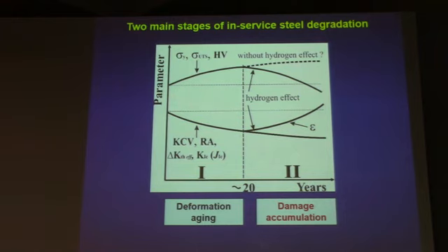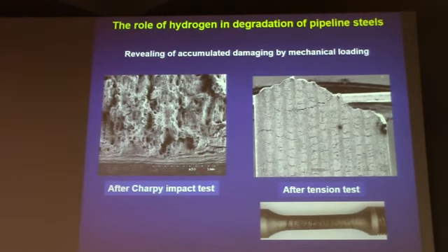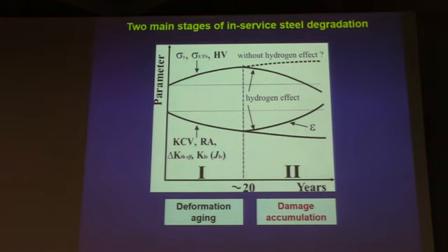Based on our previous results, we have distinguished two main stages of in-service degradation. The first stage is deformation aging, and the second one is damage accumulation. It's known that under strain aging, strength and hardness increase, and plasticity and brittle fracture resistance decrease. However, this tendency of mechanical property changes can be violated if the metal undergoes in bulk multiple damage accumulation. And in such a case, strength and hardness decrease, but elongation increases due to this problem. And further operation of the degraded metal leads to additional decrease in reduction in area and brittle fracture resistance characteristics.